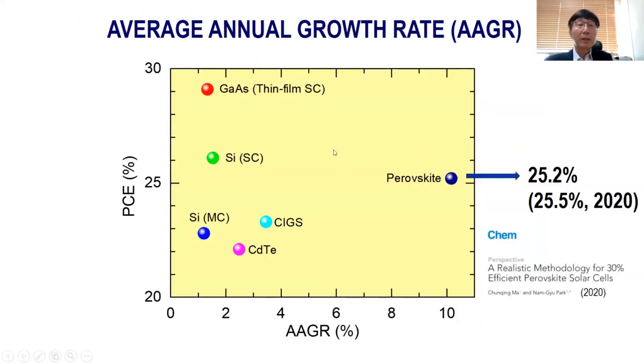In terms of the average annual growth rate of the power conversion efficiency, perovskite is determined to be more than 10%, which is indicative of a very rapid increase in the power conversion efficiency, as compared to the conventional inorganic semiconductor solar cells. Now the perovskite solar cell reaches 25.5% efficiency, which was recently reported in the best efficiency chart on the NREL webpage.